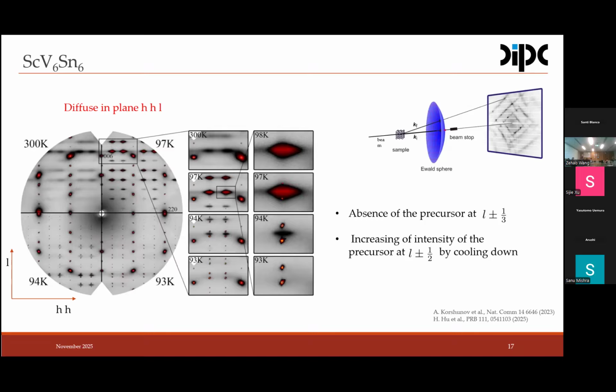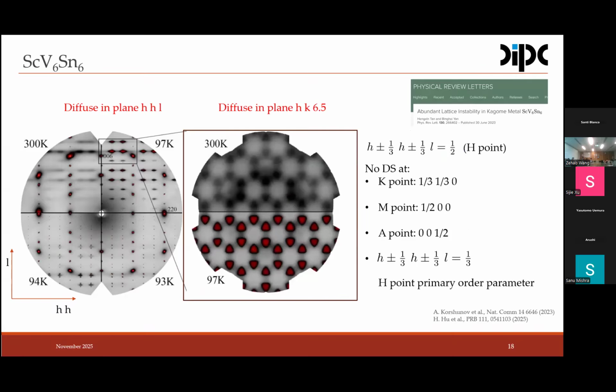I will show you later from the DFT calculations that this corresponds to the trigonal tin, just slightly above and below the Kagome plane. So if we look then at the HK plane 6.5, we actually see that the diffuse scattering has this triangular shape.